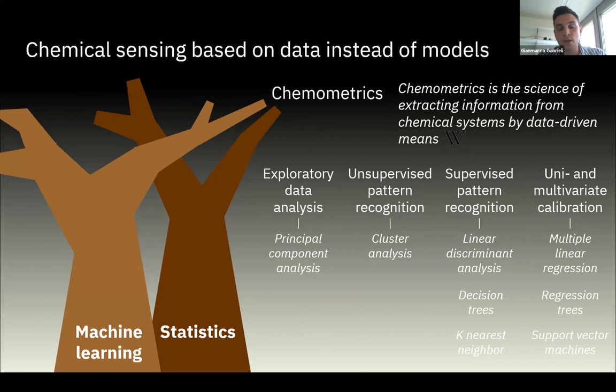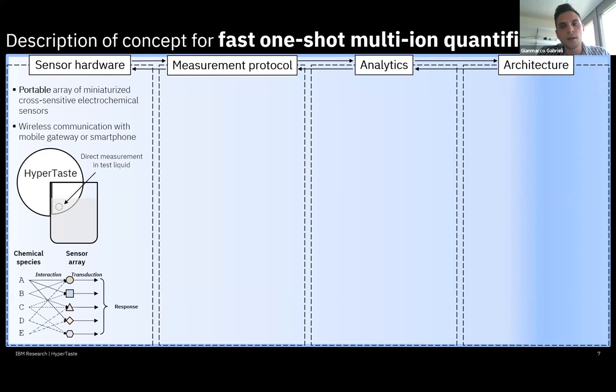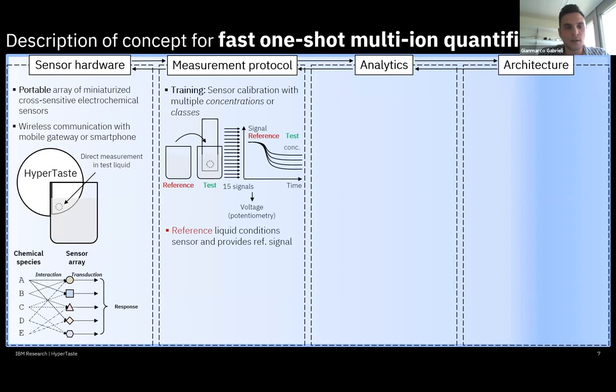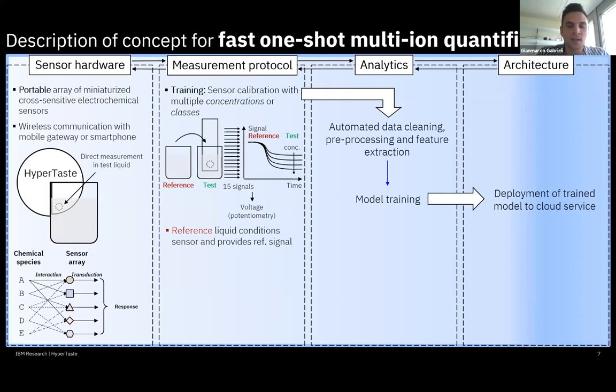So with HyperTaste, we use this portable and miniaturized device, without a physical connection but with wireless communication to a smartphone, for direct measurement in liquid. We expose the sensor array first to a reference liquid and then to a series of test liquids that we use for training the system. Specifically, we measure voltage values thanks to the potentiometric response of conductive polymers. And we use the reference solution to condition the sensor and to provide a reference signal. When we collect enough data for training, we are then able to pre-process those data, extract the features, and deploy the trained model on a cloud platform.